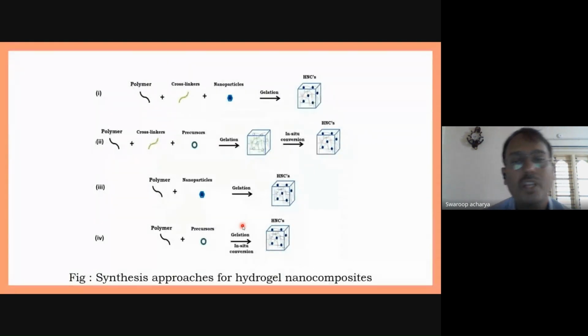Okay. So how is it being done? For the preparation of hydrogel nanocomposites, there are 4 preparation methods. The first 2 are chemical cross-linking techniques. In the first technique, the monomer or the polymer will be used, the chemical cross-linker will be added, and the ready-made nanoparticles will be added. The gelation process by means of this chemical cross-linking will be done, and the final hydrogels will contain the nanoparticles embedded within the hydrogel networks.